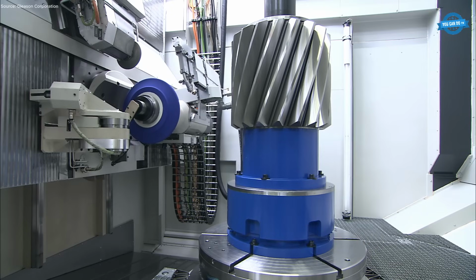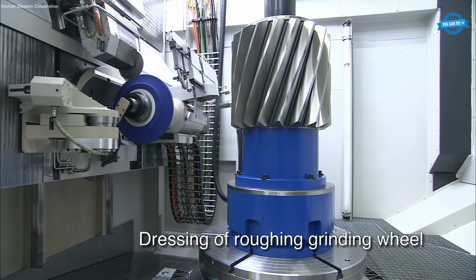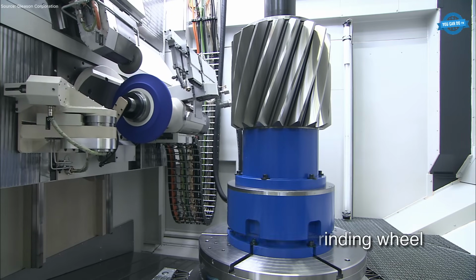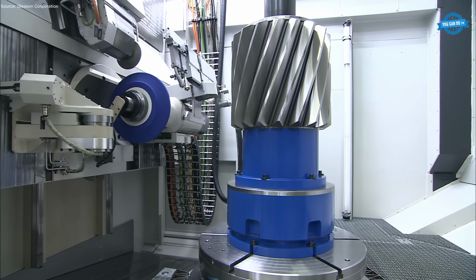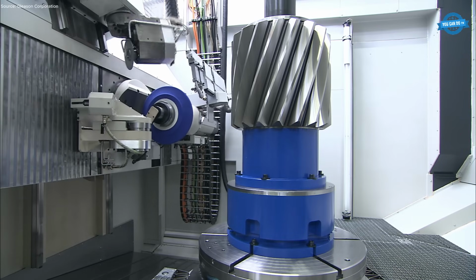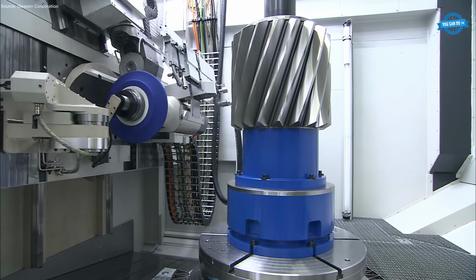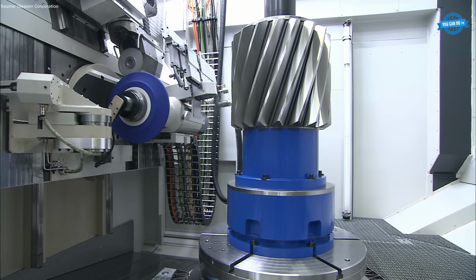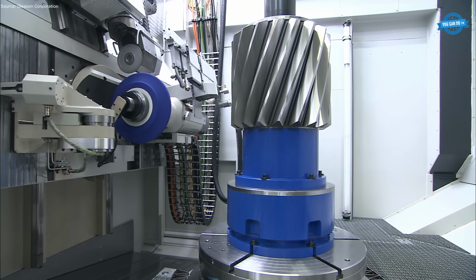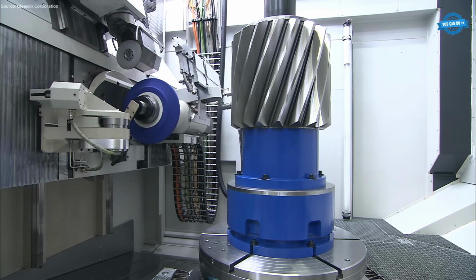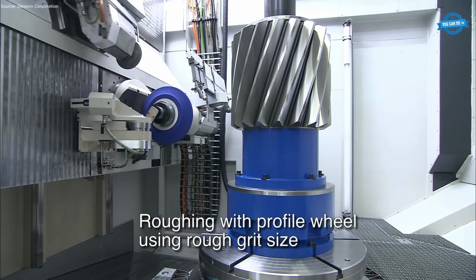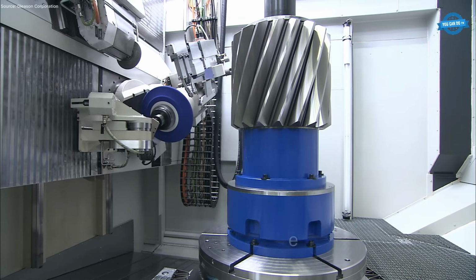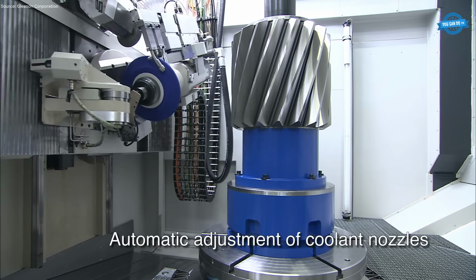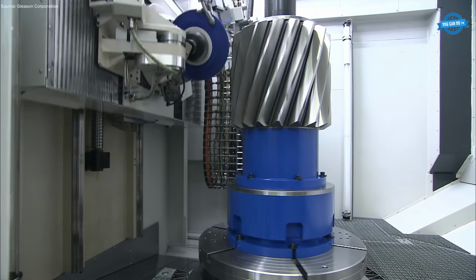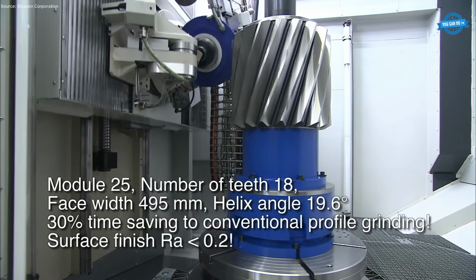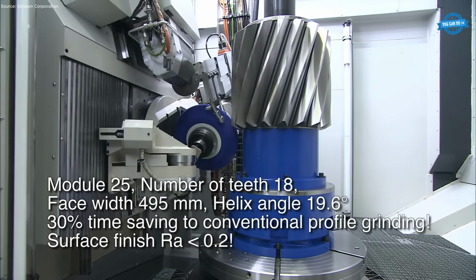When producing large module gears up to 44, the power grind function comes into play. The roughing grinding wheel is dressed, then a coarse grit profile wheel is used for aggressive stock removal. Automatic coolant control keeps the process thermally stable. For a case such as module 25, 18 teeth, face width 495 mm, helix angle 19.6 degrees, the system delivers 30% faster grinding times and surface finishes as fine as Ra less than 0.2 micrometers.